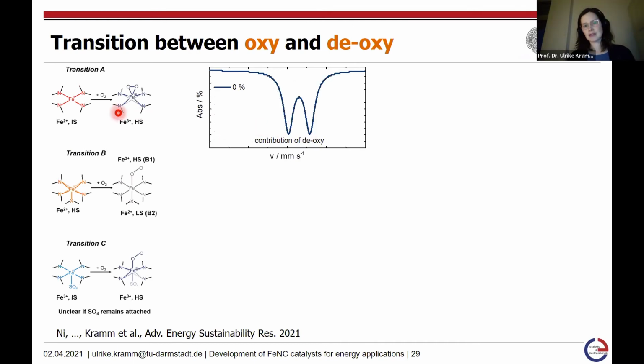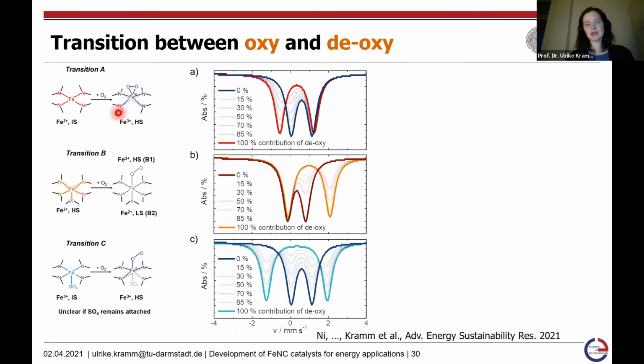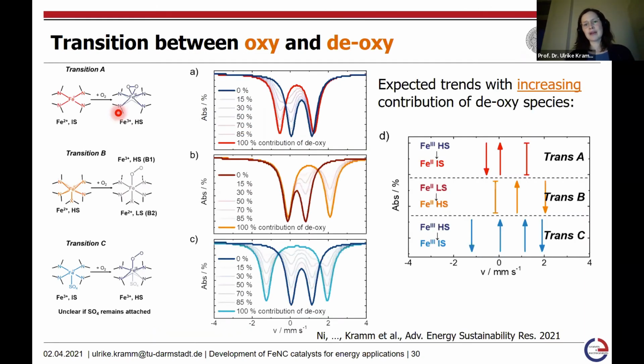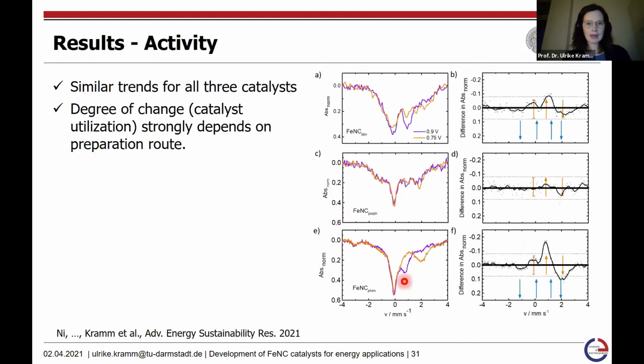Just to show you how this might develop without the contribution of the deoxygenated state, it looks like this. If we then stepwise increase it, we go into this direction. You can also play around with the other two transitions, and you will obtain this kind of graph. Based on that, we can summarize this graph into this one, which shows that, for instance, here there is no change, here this will decrease and this will increase, and based on that we have this code, let's say, for the arrows. Similarly, you can develop codes for the other two transitions in order to compare them with the in situ Mössbauer spectroscopic results. So these are the spectra for the oxygenated and the deoxygenated state.